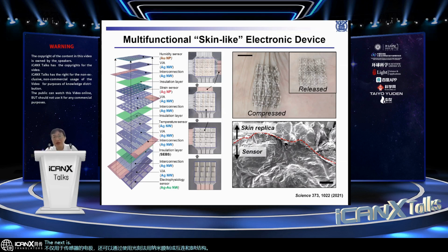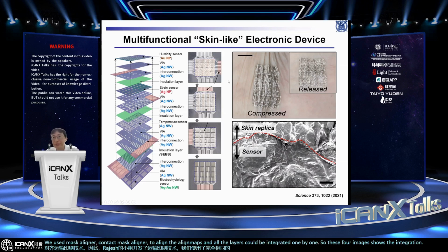The next issue is how to integrate these materials one by one, and to integrate these individually patterned nanomembranes, we used aligned transfer printing technique. So as the Rogers group developed the transfer print technique, and we used exactly the same process. We used a contact mask aligner to align the align marks, and all the layers could be integrated one by one. So these 4 images show the integration process from the bottom layer to the top layer.